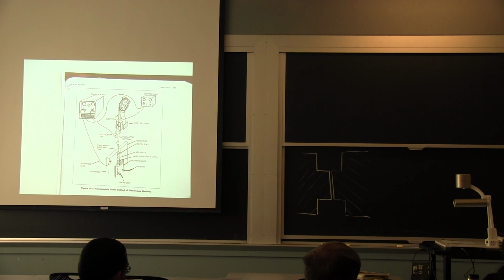If you want to, I got to re-etch it sometime. It's been 30 years since it was etched. You can see on the backside where it's not even etched. You can actually see the weld. This is a 2-inch thick plate. 2-inch thick titanium plates with a gap here. You can see where the water-cooled copper mold was on here. And the weld is this thing that's about 2 inches by 2 inches.